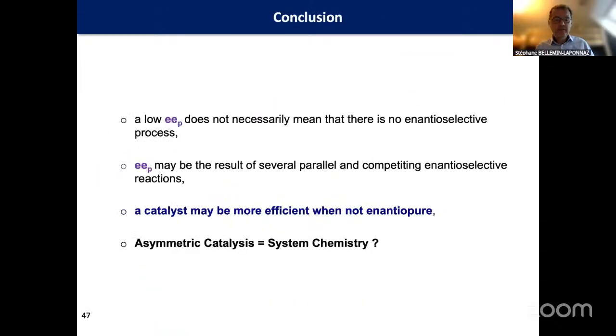So in conclusion of my presentation, what I wanted to share with you is that if you have a low enantiomeric excess in the reaction when you use a chiral ligand, it does not mean that the reaction is not enantioselective. This means that you can have competitions between active species, and the results could be racemic. And this means that the enantioselectivity can be the result of a large amount of active species that are competing